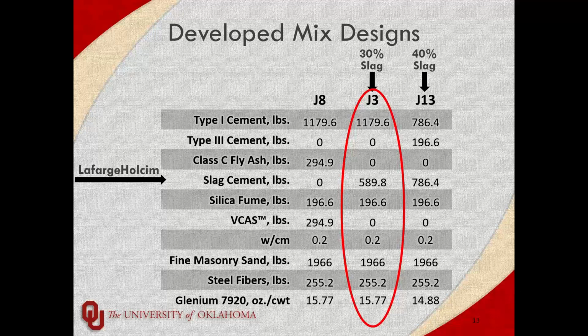J3 was the one we seem to get, we'll say, the best workability versus strength to work with. So J3 was the one we decided to use for some of our bigger scale testing and our bond testing, because while we wanted strength and it wasn't necessarily the strongest mix that we had, it did have the best workability while maintaining a high level of strength. And workability in repairs is very important, especially when you use UHPC, because the benefit of using UHPC is its strength, and because it's so strong, you can use much smaller repairs and much smaller joints. And because they're so small and they can be congested, you need a highly flowable mix to actually get to all those recesses. So J3 struck that balance between workability and strength that we were looking for. So we went ahead and did most of our big scale testing with that. Next slide.